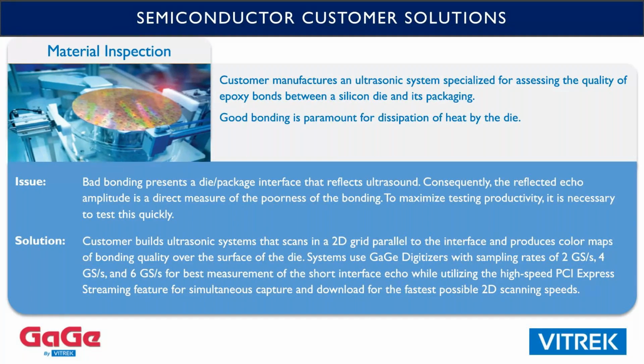So in fact, you sort of know where to expect the echo from the interface between the die and the package. And if you look there, the amplitude of that echo is a direct measure of the poorness of the bonding. You can then scan parallel to the die surface, and then produce a color-coded map of the bond quality over the entire surface of the die. And you can actually produce an average bond quality index that then is used to produce a pass-fail criterion for the chip.